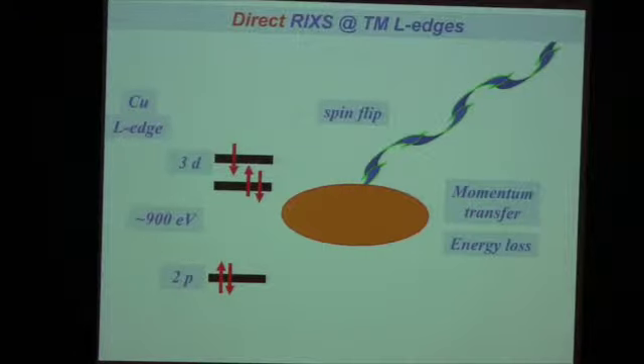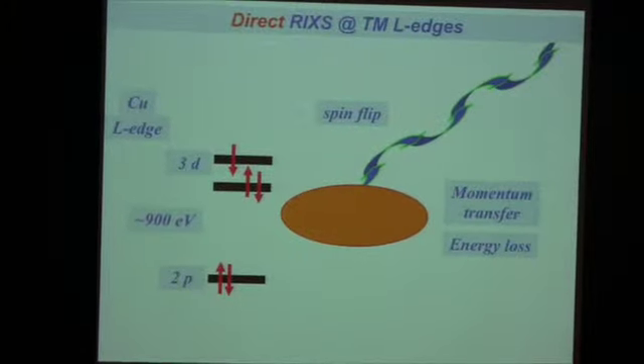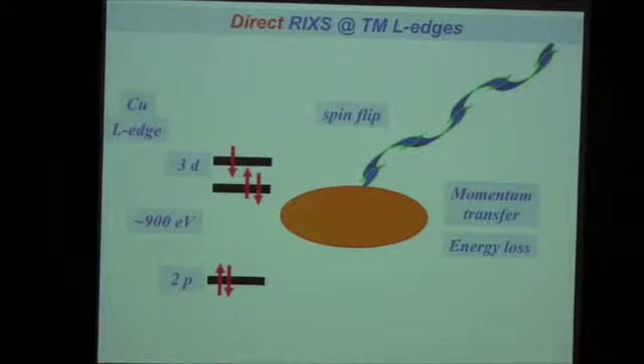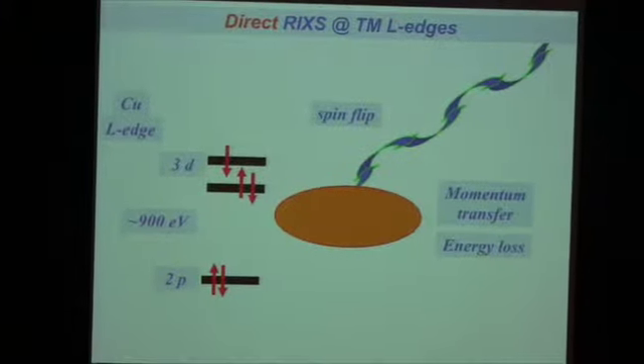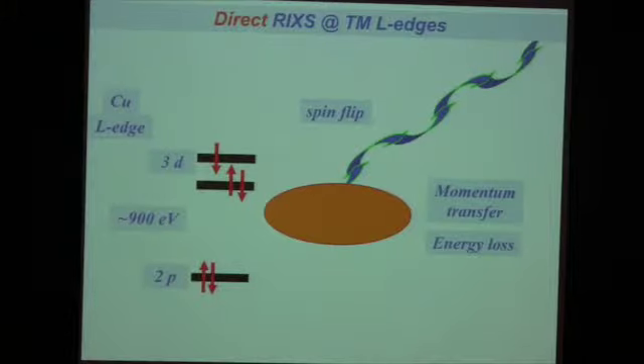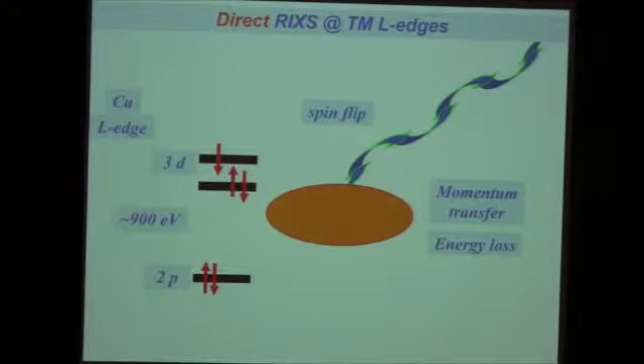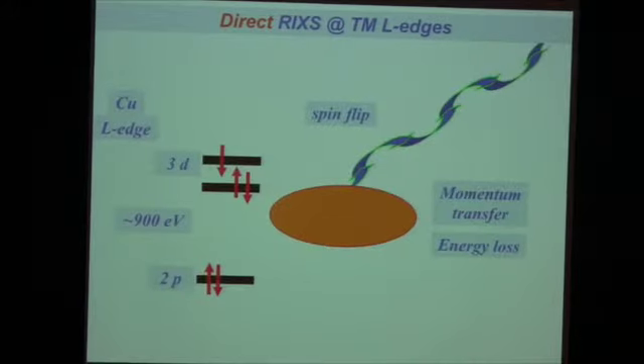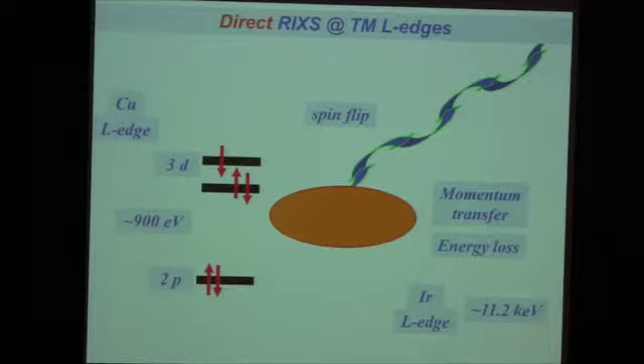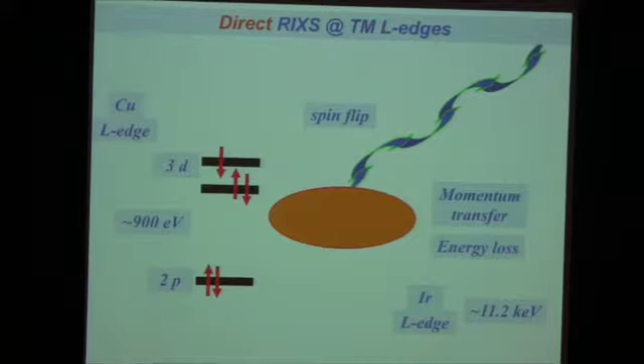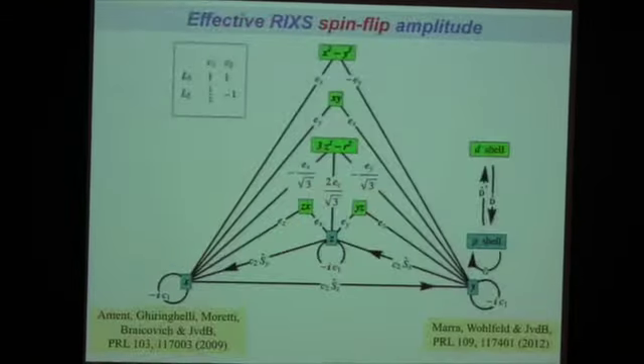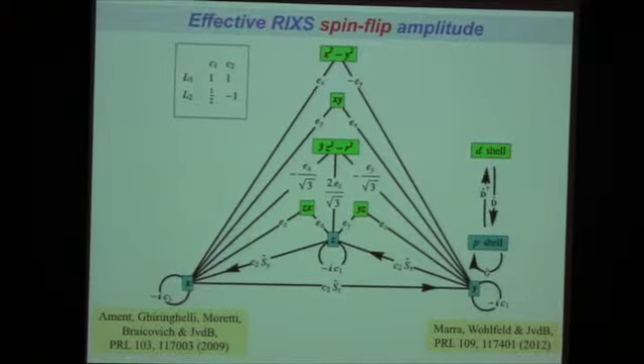So now the point is, again, I did RIXS. I had some complicated intermediate state with the core hole. This core hole has spin orbit coupling. All fine, but the end result is very simple. I started with a spin up, and I end up with a spin down. It's just like neutron scattering, effectively. And you can do this in iridates as well, but then you will be in the hard X-ray regime. It will be 11 kilo electron volt or so, the energy of the photons. Anyway, so that's also in this diagram.